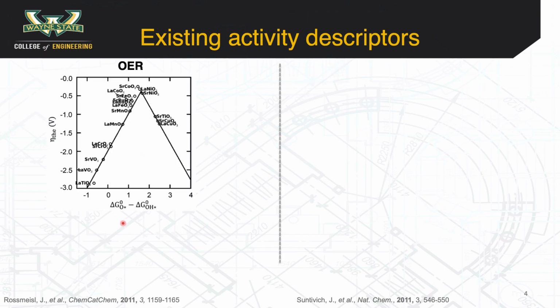Despite these challenges associated with identification of predictive tools, there has been some work towards identification of activity descriptors that serve as predictive tools. For instance, the theoretically calculated adsorption energy difference between oxygenated intermediates O and OH has been shown to exhibit a volcano type relationship with a theoretical overpotential for oxygen evolution reaction. Oxides on the left leg of this volcano are limited by strong adsorption, while oxides on the right leg are limited by weak adsorption. Oxides close to the top provide an optimal compromise between strong adsorption and weak adsorption, thus leading to enhanced catalytic performance for OER.